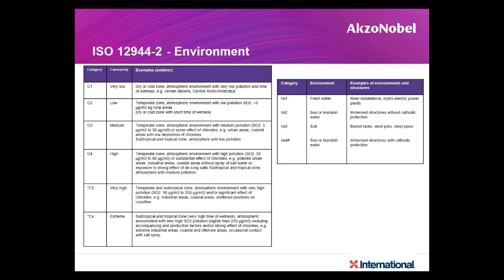Such places are in controlled substrates. C2 is low: temperate zone, atmospheric environment with a lower level of sulfur dioxide, dry cold zone with very low wetness, short time of wetness. Medium is C3, temperate zone. For example, C3 can be somewhere in the middle of Bangalore city. Little effect of chlorides, some amount of exposure to pollution, but not very corrosive.